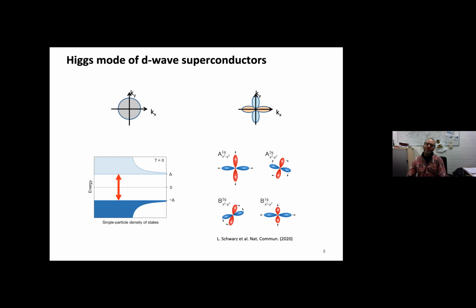However, there is one problematic part. In these S-wave systems, we have seen we had these nice ringing oscillations after quenching the superconducting condensate. And the reason is because in an S-wave system, the superconducting gap is open in the whole momentum space, and hot quasi-particles are always separated from the superconducting condensate by a full superconducting gap.